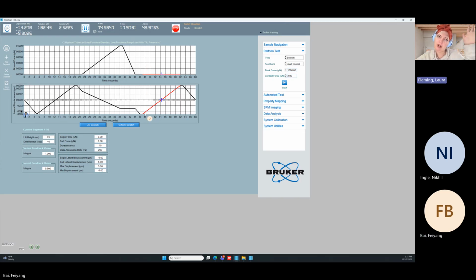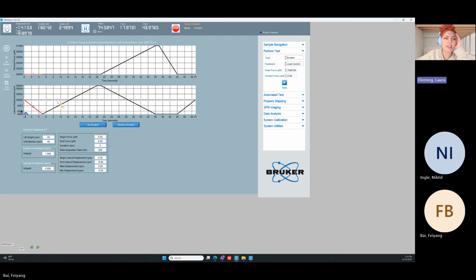You just do the little pre-scratch, you do your actual scratch, and then you're done. With tilt, it only has this first part where it traces. In that first part, it's tracing over the sample surface to see the normal displacement change as a function of the lateral displacement so that we can correct for it, right? Then this is where the actual scratch occurs, either with a ramping load or with a constant load. And then that's where this one ends. Basically, you unload and you come back to zero, in both the normal force and the lateral force.